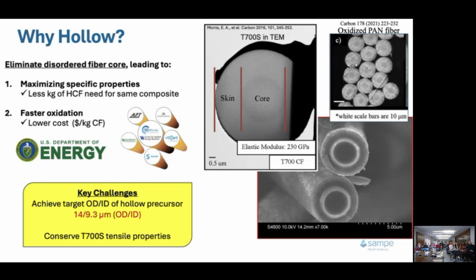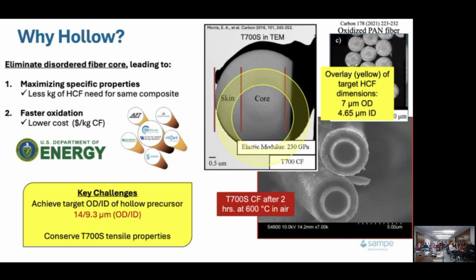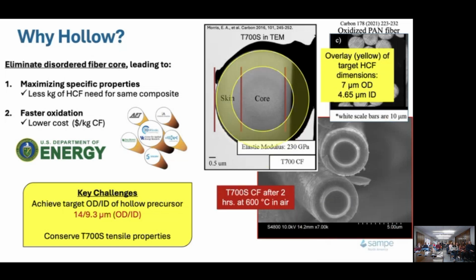We took some of Toray T700, chopped it into bits and put it into a TGA, heated that up to 600 degrees over a couple hours. And you can see that it essentially selectively burns out the less oriented carbon, leaving these pits on the ends of the cut filaments. So we've proposed to essentially spin a hollow fiber and make more efficient use of the carbon that is there, on the basis of the mass of the fiber, so the density.